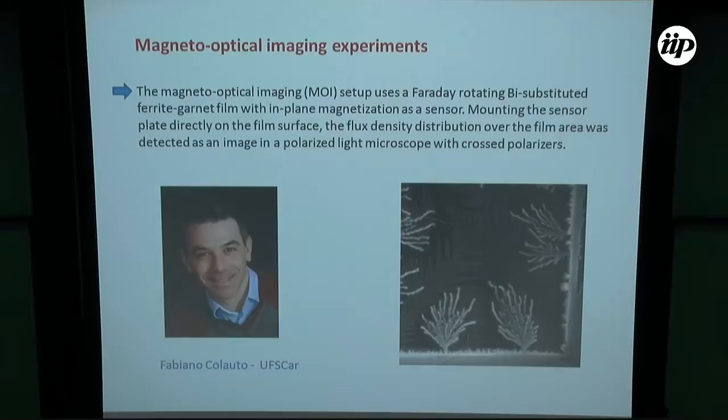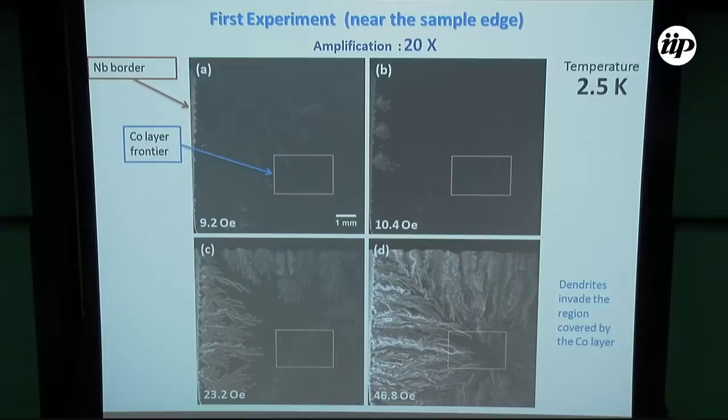Okay, so I'll show you some experiments. This is our first experiment, just for testing the idea. Here you may see the position where the cobalt layer is placed, and the rest is niobium. And the field is applied, temperature is 2.5 Kelvin, and you see the vortex, the flux avalanche advancing inside the film. This is 23 Oersted, and then the avalanche eventually reaches the area covered by the cobalt layer and penetrates without